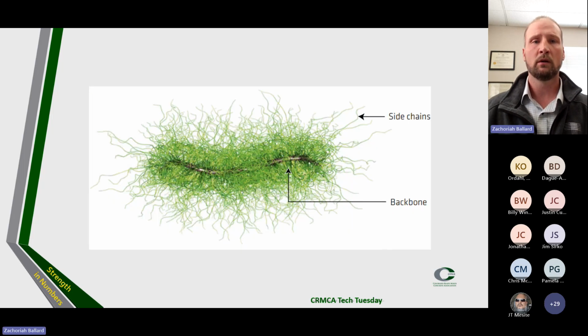So, quick background on some of our polycarboxylate ether-based superplasticizers. It's a targeted polymer design to specific concrete properties. The mode of action is based on the adsorption of the polycarboxylate onto a cement grain, and dispersion of particles by electrostatic repulsion and steric hindrance.